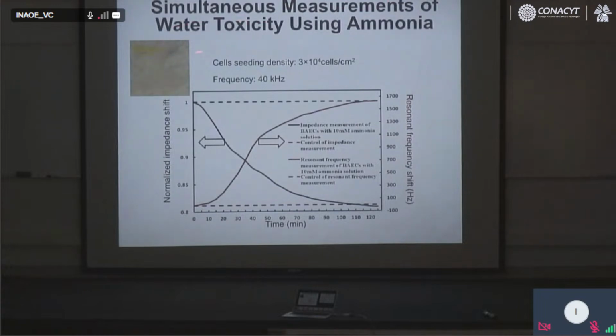Simultaneous measurements of water toxicity using ammonia. So I think this graph is good, because in this graph you can understand how the two sensors are behaving when we introduce ammonia. So this is the resonant frequency. What happened? When you introduce ammonia, the cells are not happy, they will die, and when they die, the monolayer is detaching from the electrode and starts to float, and the resonant frequency is coming up.